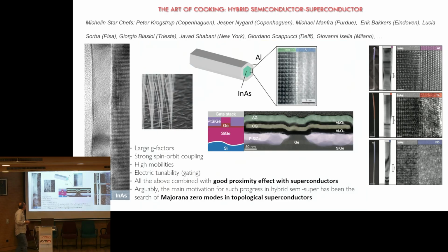All right, so again, the ingredients that you need are a strong spin-orbit coupling, which comes from the semiconductor. Large g factors, because you want to break time reversal symmetry. You want to put large Zeeman fields without killing superconductivity, and this you can accomplish with large g factors. High mobilities of the semiconductor, gating tunability from the semiconductor, and all this combined with superconductivity can give you these kinds of exotic states with Majoranas.